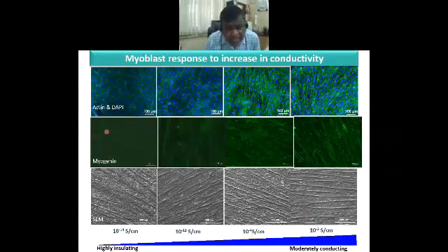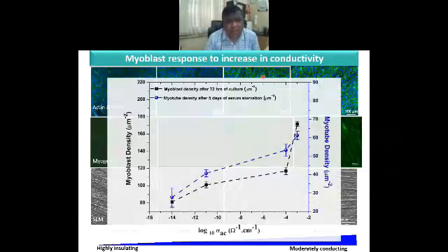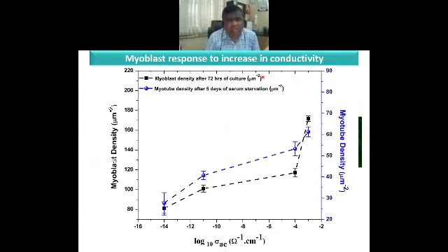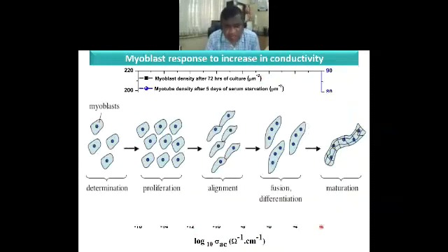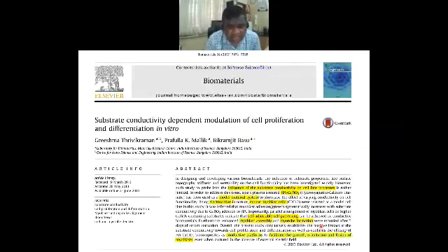Now, when you grow muscle cells without electrical stimulation, we have seen that as the conductivity increases, the muscle cells are organized in a very nice manner, leading to myotube formation. Myoblast density and myotube density are both modulated in an electrical conductivity dependent manner. This is shown here: first the myoblasts proliferate, then align, then fuse, and then form matured myotubes. In all these cases, we have observed the role of substrate conductivity as one of the important parameters to modulate cell proliferation and differentiation in vitro.